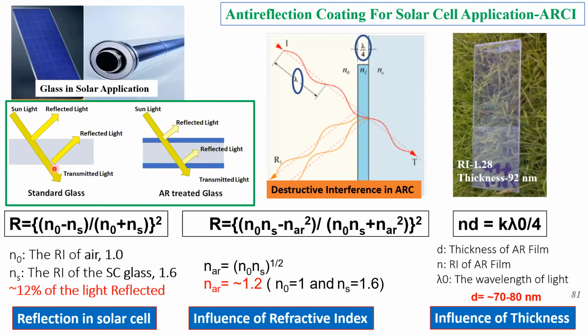When light falls on any substrate, as per the Fresnel equations, around 12% of light gets reflected by both surfaces. But when we put an anti-reflection coating, we can create destructive interference. Everybody here is, I hope, very much aware of destructive and constructive interference, which we studied. The same basic phenomenon is used here to fabricate the anti-reflection coating, so that we can convert the reflected light into destructive interference and reflection will be almost zero. If reflection is zero, we know that T plus R plus A is equal to 1. Absorption will always be constant, so transmission should improve. Based on this, we can tell that transmission is very much better.